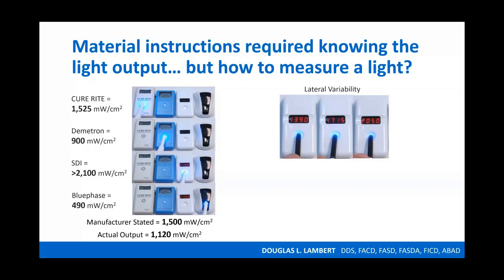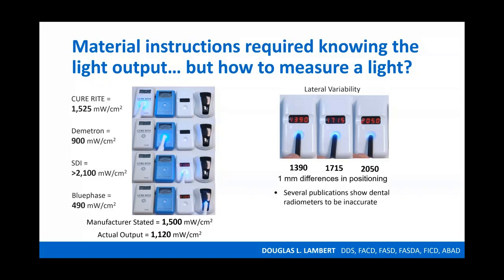And lateral variability, how you hold the light tip, and how it varies by as little as 1 millimeter, can make a big difference in the output of the energy. Several publications continue to show that radiometers are inaccurate, but for some of the radiometers, the size of the aperture is not the same size as the aperture of the light itself. So really they should correspond to be the same size, the light tip and the aperture in the radiometer, to really give you the most accurate reading. And none of the radiometers are up to ISO standards. So again, we are using the best data that we have at the chair right now if we're using a radiometer at chairside, until we talk about new technology.